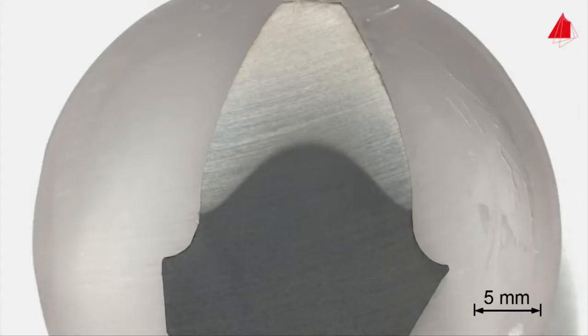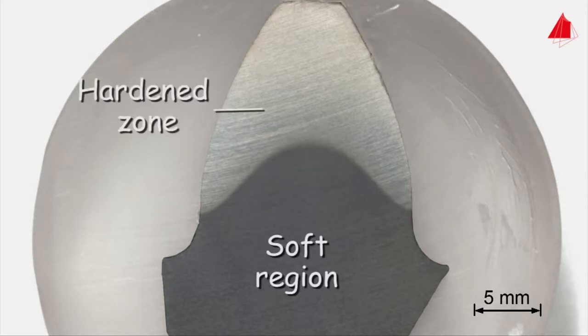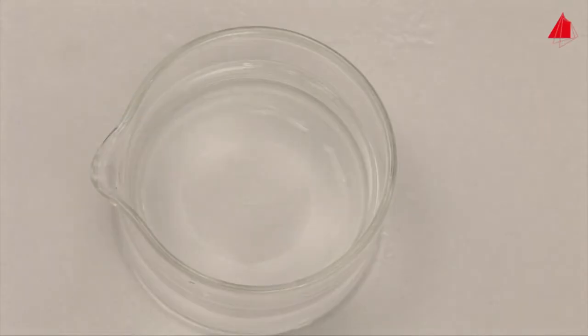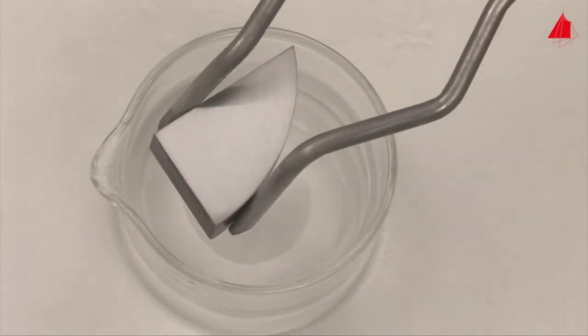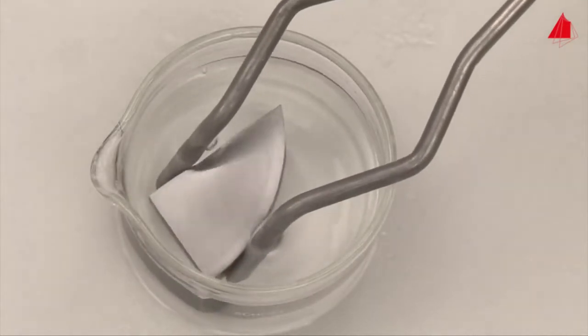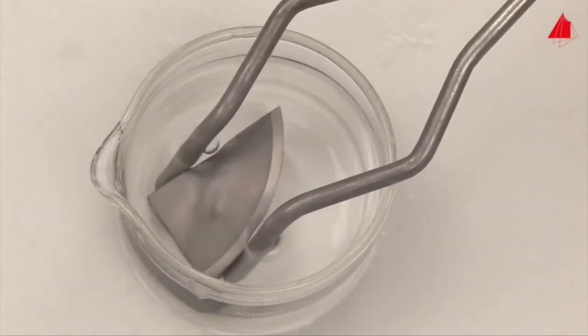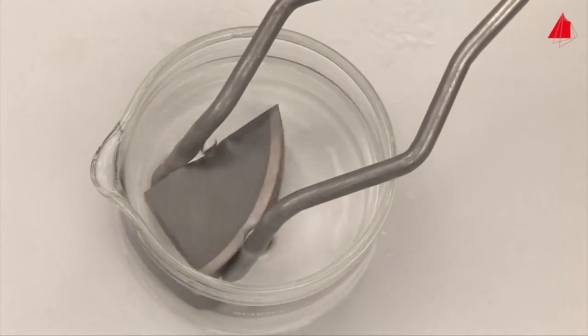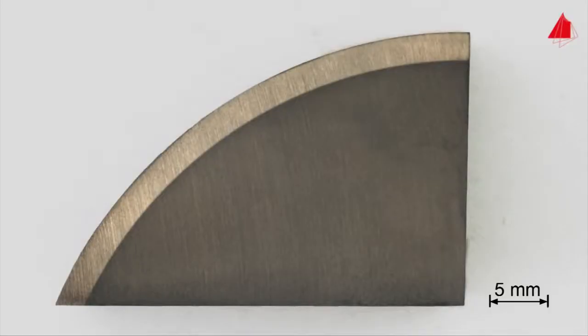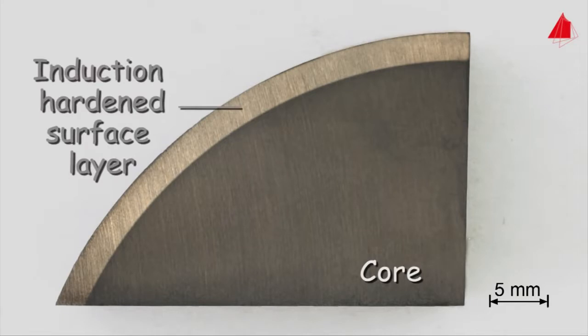In this case, the individual grains cannot be seen, they are far too small. But what may be seen very well is the hardened zone, which appears light, and the central soft and tough region, which appears dark. Next in line is the section of an induction-hardened cylindrical shaft. The comparatively soft core is much more affected by the etchant than the hardened surface layer. Clearly, the induction-hardened surface layer can be distinguished by its light color from the darker core.